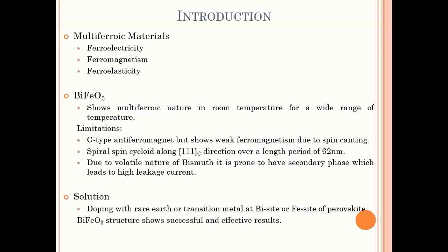The material that my work focuses on is bismuth ferrite, mainly due to its room temperature magnetoelectric behavior for a wide range of temperature, which makes it suitable for application purposes. However, it has some drawbacks. For example, even being a G-type antiferromagnet, it shows weak ferromagnetism due to spin canting, but a spiral spin structure generated from Dzyaloshinskii-Moriya interaction cancels out the macroscopic magnetization.